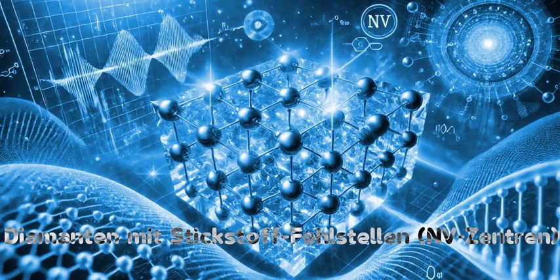How does that work? Schnepp explains that the zero field splitting, that D value, actually changes slightly with temperature. It has a known temperature dependence, roughly negative 74 kilohertz per Kelvin. So if you measure D very precisely using ODMR, you can calculate the local temperature. And because the NV center is so small, you can get temperature maps with incredible spatial resolution. Think nanoscale thermal imaging inside a chip or even a living cell. Tiny quantum thermometers.